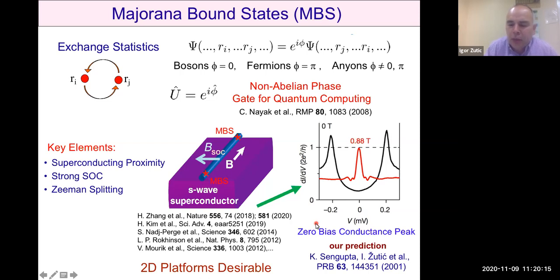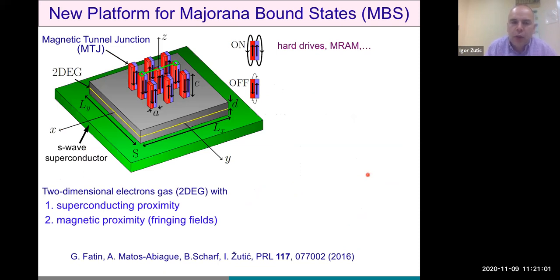As a side remark, we may have been first to predict that almost 20 years ago. However, these zero bias conductance peaks can be tricky. They may occur for other reasons, not because we have Majorana fermions. And perhaps the most exciting aspect of having these non-abelian statistics is really not encoded in this zero bias conductance peak. So if we would like to exchange these Majorana states, we should really go away from one-dimensional geometry. We should try to seek two-dimensional platforms where this exchange, or so-called braiding, of Majorana fermions would be much more natural. So to this end, we consider the following structure.